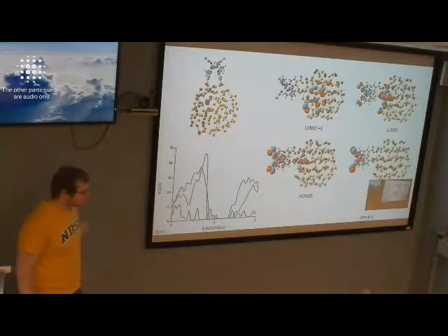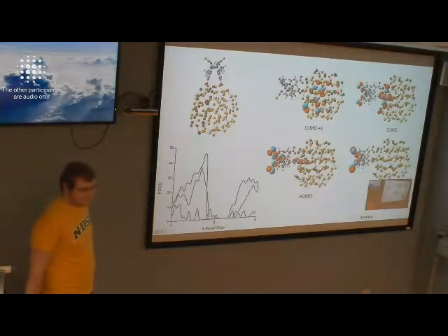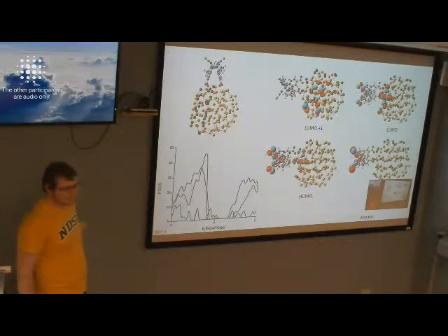So first of all, we need to calculate the dye, and since you're doing vacuum calculations, you also have to calculate your dye in a vacuum to see what happens with the DOS. As I said previously, we saw really bad behavior of the DOS for the dye in vacuum, because we have this artificial charge transfer state, and when you put in solvent, the polar media, this artificial charge transfer state disappears, and then your gap is opening.